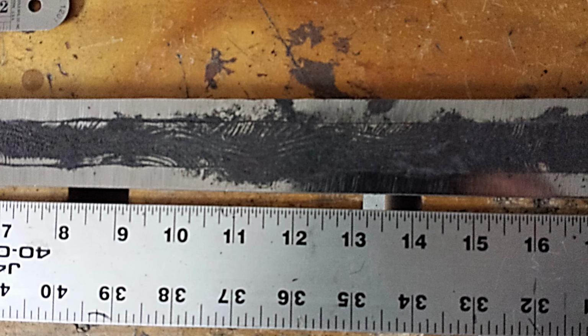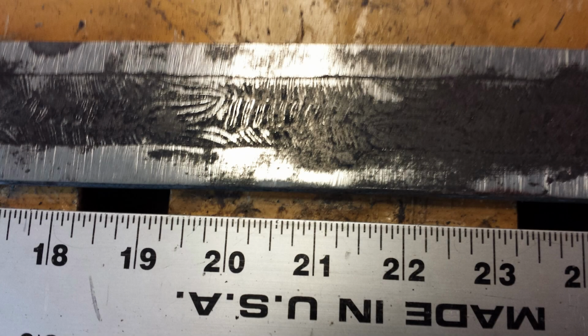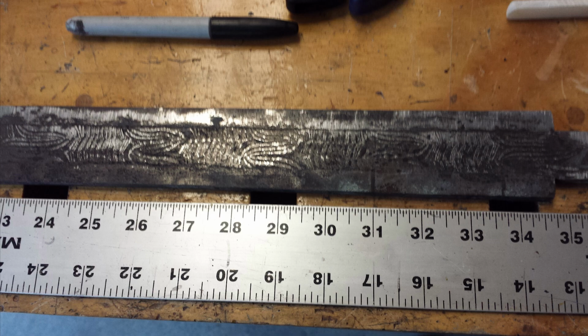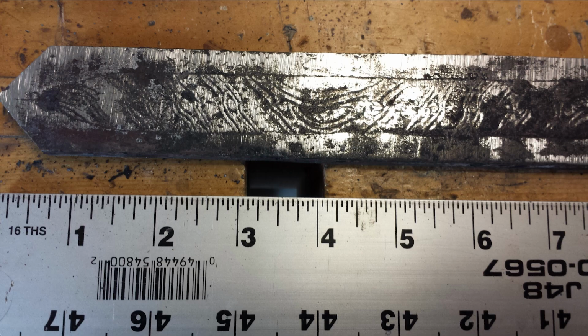Unfortunately, the serpent pattern had stretched out too much during forging. I apologize for the bad quality of the images, but these are the only pictures I have left. This one here shows the transition between the 2-bar pattern to the 3-bar pattern. The chevron is straight. The checkers look like it would need a bit more grinding than anticipated to get to the center of the bar. Sorry again about the quality of the images.